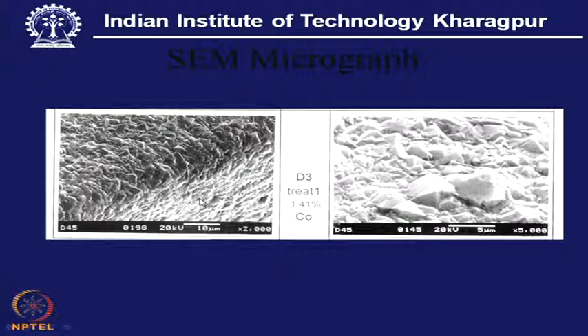So, recording of this picture is so essential, with much clarity that this is the face and flank of the tool that is well built with this coating, and there is apparently no micro void or cracks. And to examine deeper, we can go for even higher magnification, if it is so needed, and the scanning electron microscope with its high resolution power gives us that leverage, that with that we can make a lot of analysis on the quality.